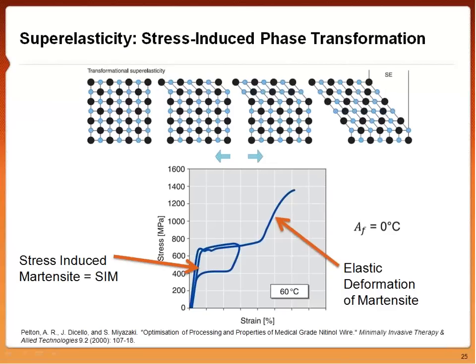So you're still going through the same steps. When you go through the shape memory effect, you cool it down, it becomes twin martensite. You apply the stress, it becomes detwin martensite. The same is happening with superelasticity. When you apply the stress, it's twinning, but as soon as it's twinning, it's tending to detwin to accommodate that stress. And so when we look at the stress-strain curve, we see that.